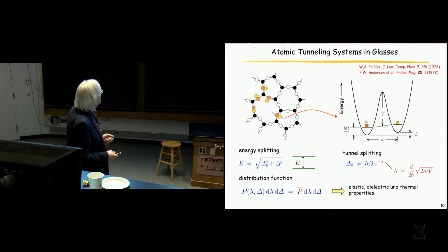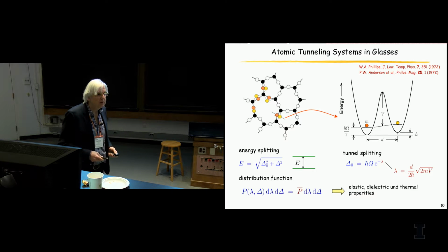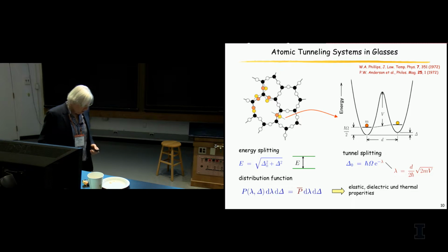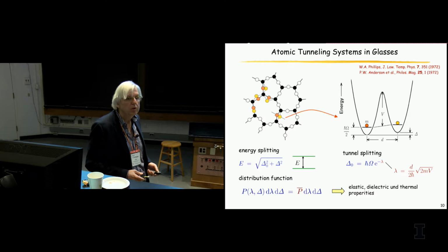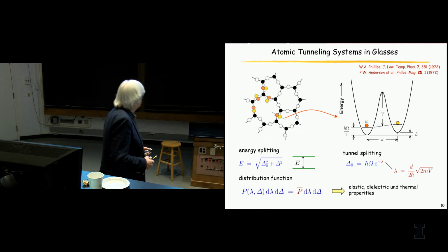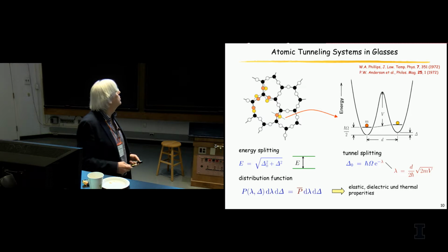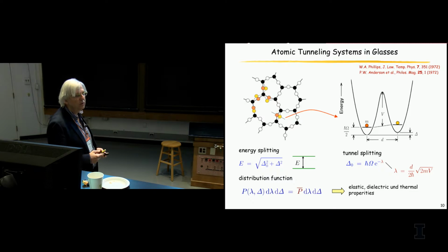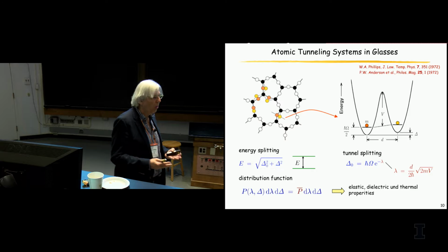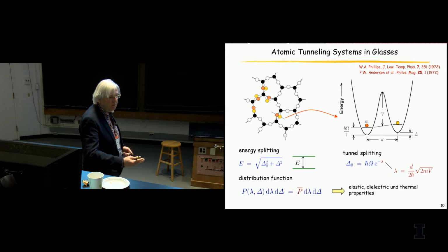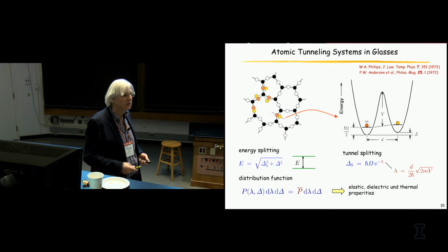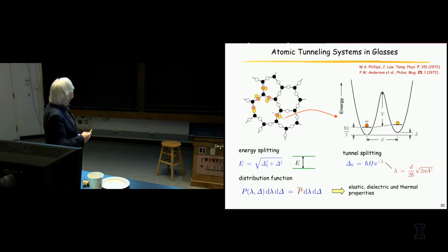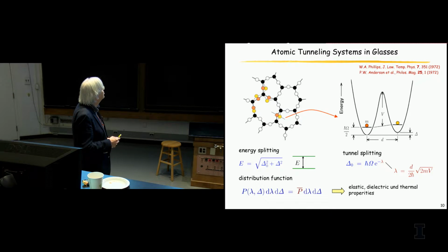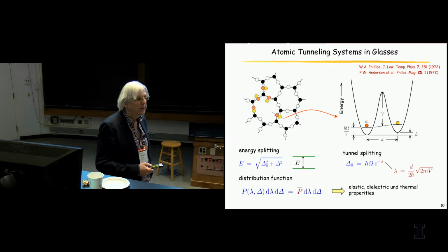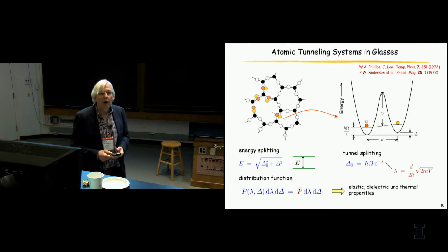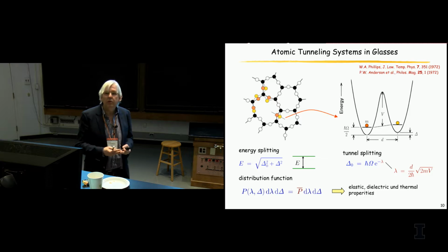Now, the canonical description still today for glasses is something which was published in 1972 in two independent publications by Phillips and Anderson and co-workers. And the idea is the following. In the matrix of glasses, you find atoms which reside in minima which are separated from a second minimum only by a small potential barrier. So if you cut through that in the potential landscape, you will find this double-well potential, and you find those two positions here. And since the barrier is not too high, the tunneling probability becomes large, and at low temperatures, you can observe those tunneling processes.